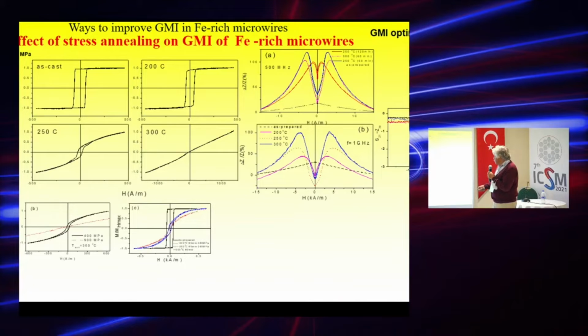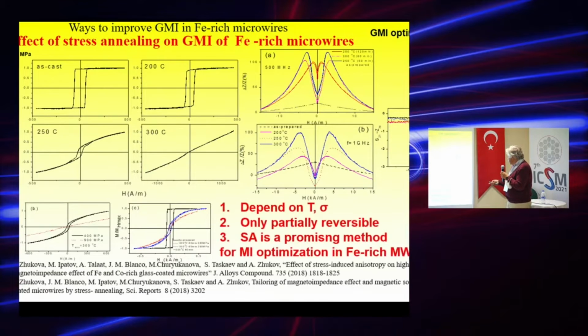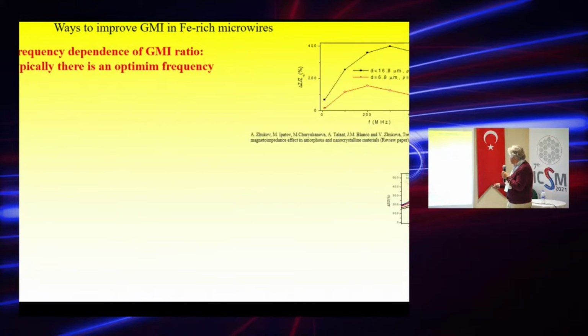And we also tried to see what happens if we apply further annealing after stress annealing. So this stress-induced anisotropy is only partially reversible. Part of this stress annealing-induced anisotropy still remains in the material. And of course, it's quite interesting because in this way you can tune properties, and it could even be temperature stable. To resume, this stress annealing-induced anisotropy depends on temperature and on stress during the annealing, and is only partially reversible. And of course, it's a promising method for optimization in iron-rich microwires.